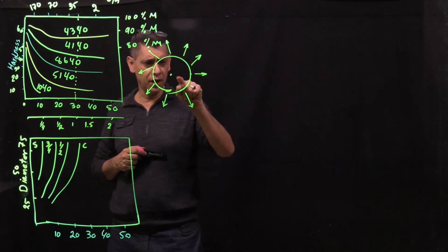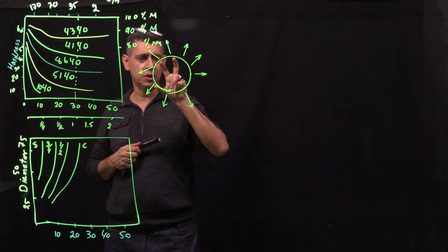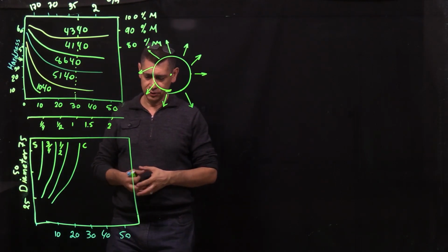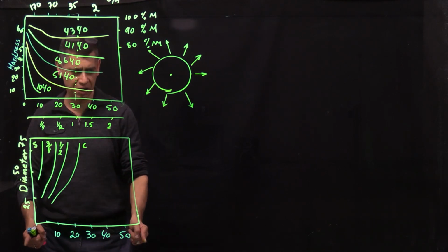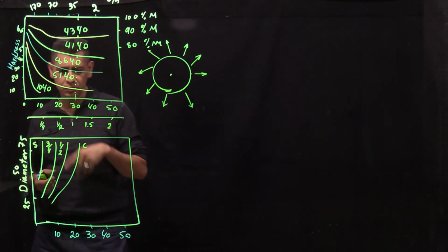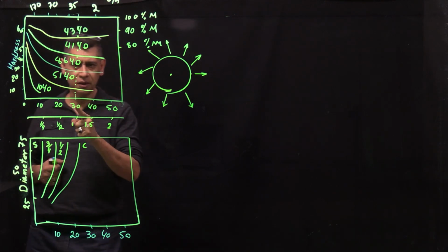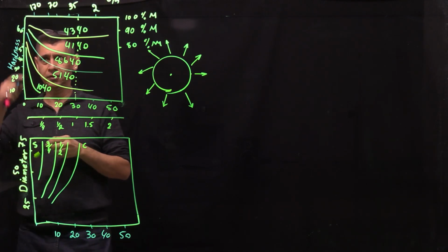So how do I try to embed this concept into the Jominy? Then you have this graph. This graph in the book, you may get the same kind of scale in an exam or anywhere else. You just read it. So I'm just saying 30 millimeters, for example, cooling rate. So you go to, for example, 4340, and this gives you this hardness right here. Okay, let's say, I don't know, maybe about 57.